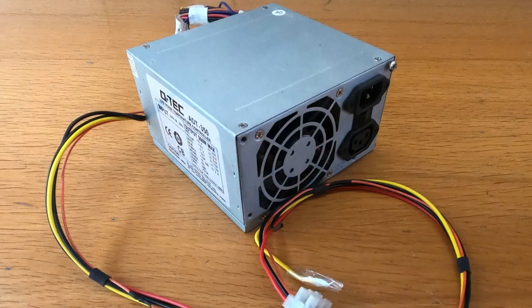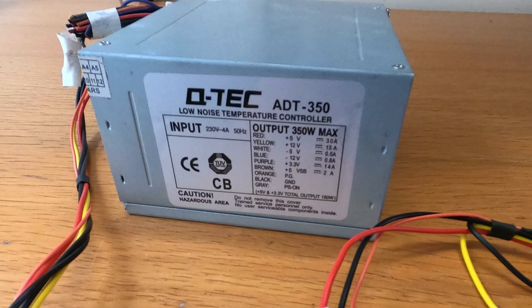For a power supply, I'm using an old PC supply. I'm using the 5V rail. You can also use 12V, but more voltage doesn't really help, it just makes the solution heat up faster.